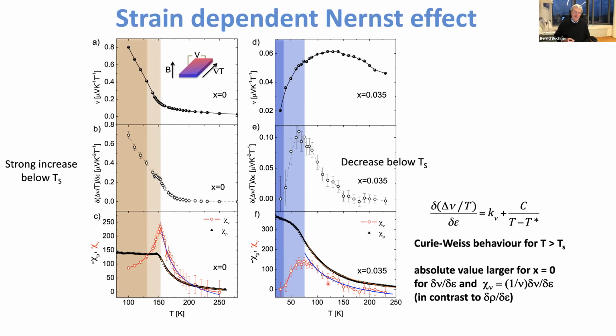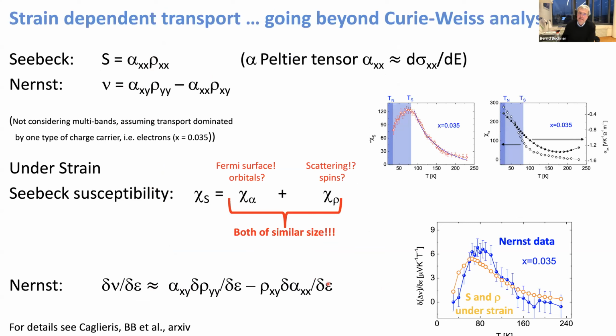And let me at least show you a first attempt at how we can discuss these things. When you write down the Seebeck effect, you take this Mott formula, and you can write it in the following form. It's a product of the so-called Peltier tensor times the resistivity. Here I assume a single band, so I forgot about all the complications due to multi-band effects. And if you do that, and this may be relevant for the doped compound, you can determine a Seebeck susceptibility, which is a sum of a susceptibility coming from this Peltier tensor, which usually measures details of the Fermi surface, plus a second contribution from the resistivity.